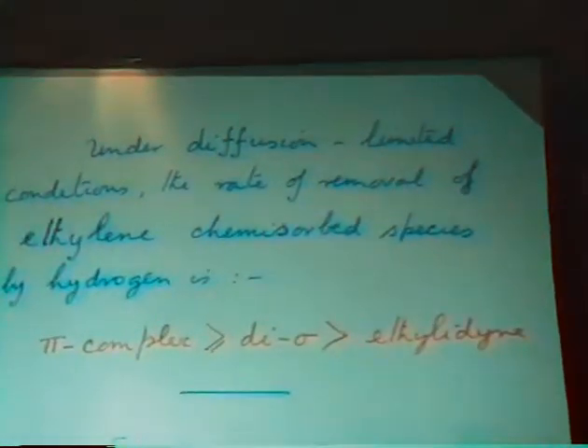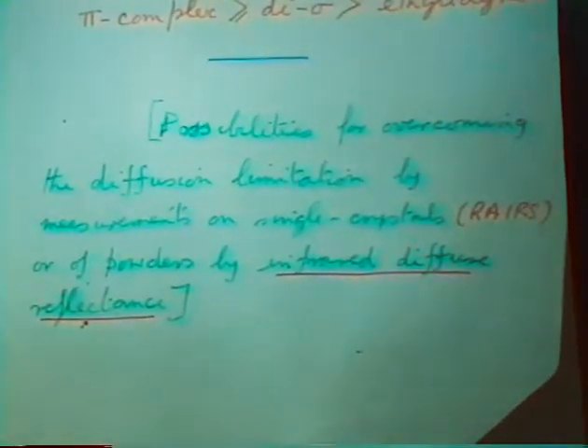There had been proposals in the meanwhile that the reaction went on the 1-1-1 face, and the ethylidyne played a role. Unfortunately, as Neil Avery quickly spotted, the kinetics were somewhat different on our sample than those normally reported, and this was obviously due to diffusion limitation of getting the reagents in and the products out of the finely divided catalyst. But at least for the diffusion limited case, the pi complex always disappeared very quickly, so did the di-sigma, though more slowly, and ethylidyne, it's part of the hydrogenation process, but it's much slower, it's not catalytically significant. And of course, in principle, one can now go back to powdered catalysts, as Bob started with, using diffuse reflection in order to study that. Well, now, I don't want to...